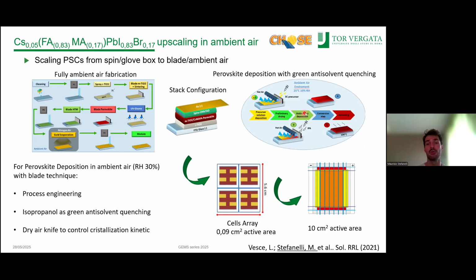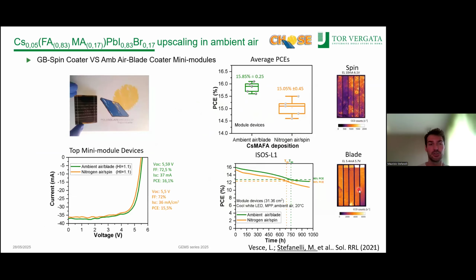With this configuration, we were able to coat substrates that are 5.6 by 7.5 centimeters, and to get from this substrate an array of small cells in order to assess not only the uniformity through different optical measurements, but also the efficiency and the photovoltaic parameters for each zone, and then we transfer them to the mini module area. Here I will show just a comparison between the mini modules that we produced, made with spin coating in a nitrogen environment and with blade coating in ambient air, as I already presented to you.